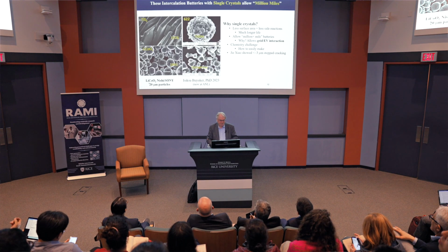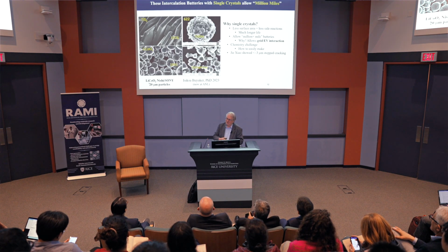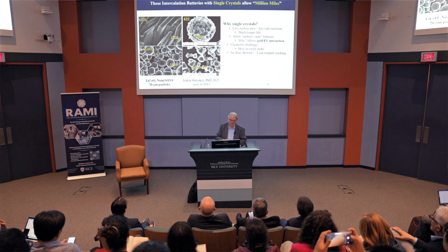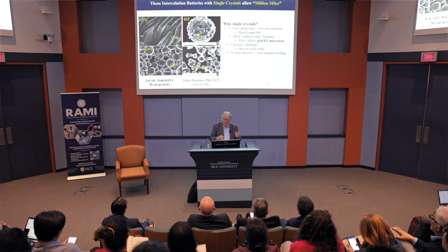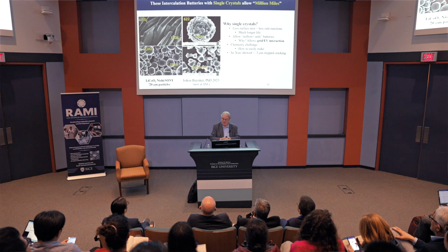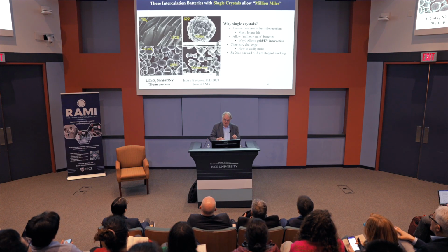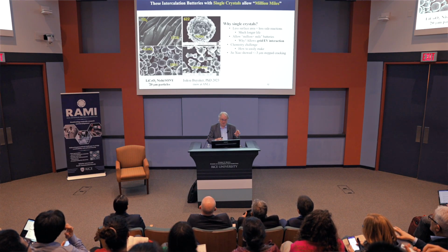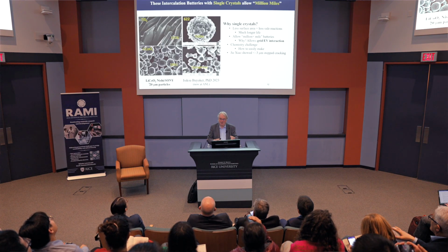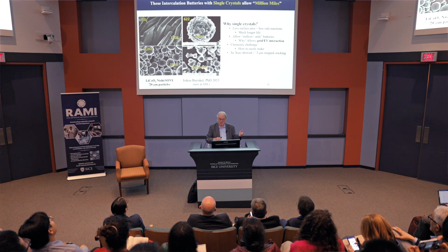Here are the typical electrodes used over the years. Left-hand side at the top is Exxon's titanium disulfide, large single crystals, very low surface area. Beneath that are Sony's lithium cobalt oxide. Sony realized these materials are hazardous, so they tried to make the crystals as large as they could. This particular picture is from Jeff Dahn, but the Sony ones were in fact 10 to 20 microns in size, the single crystals. I should point out the Exxon ones, in the basal plane, these crystals were more than a millimeter in size.